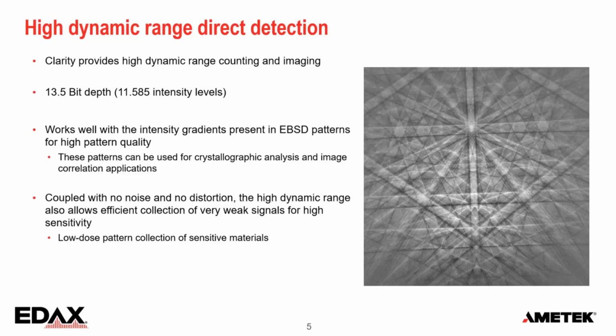And if you just collect enough electrons to fill the wells in the sensor, you get very vibrant EBSD patterns with lots of detail, because we can distinguish all the different gray levels, different intensity levels. And when you do that, you can work very nicely with the intensity gradients that we have in EBSD patterns. You get very good pattern quality, and you can use that for crystallographic analysis, combinations with dynamic simulations, image correlation applications, etc. They're very nice, sharp images.